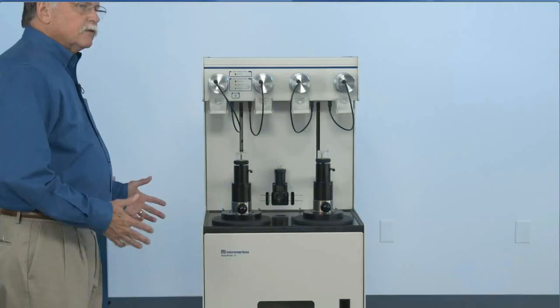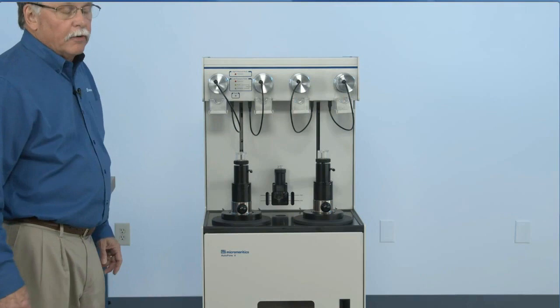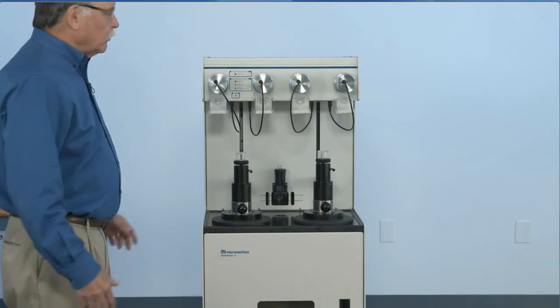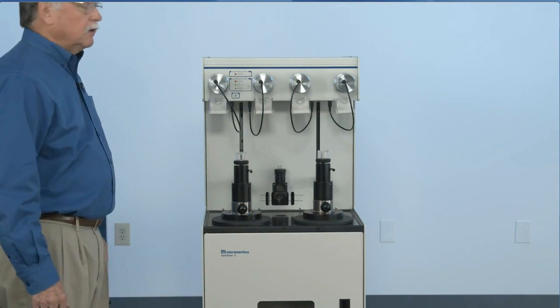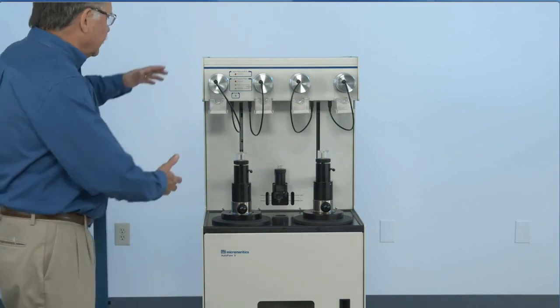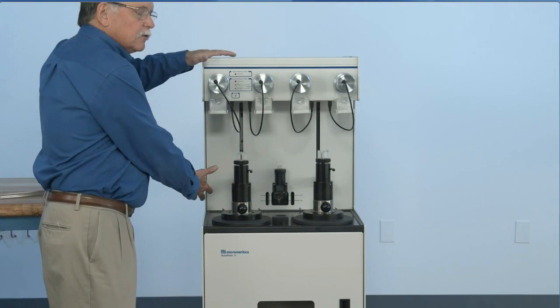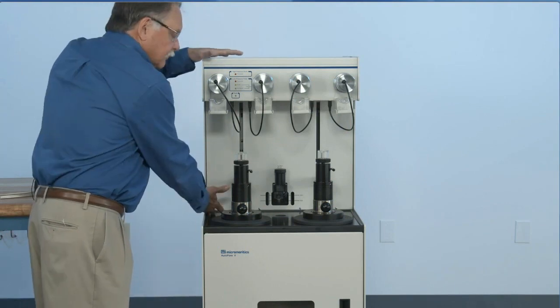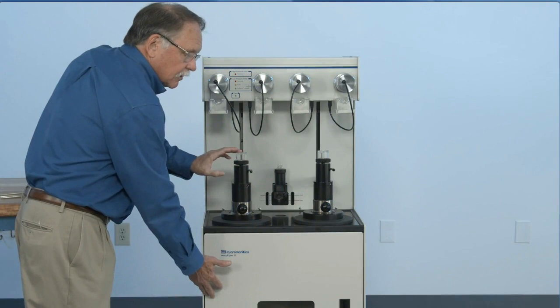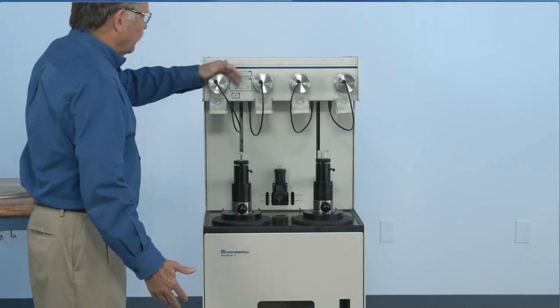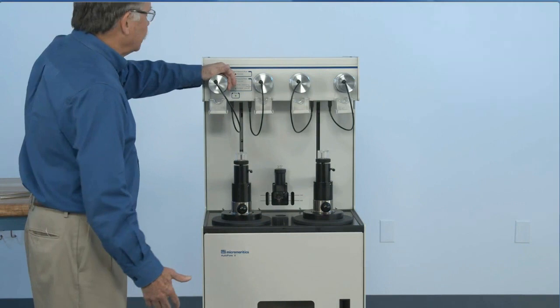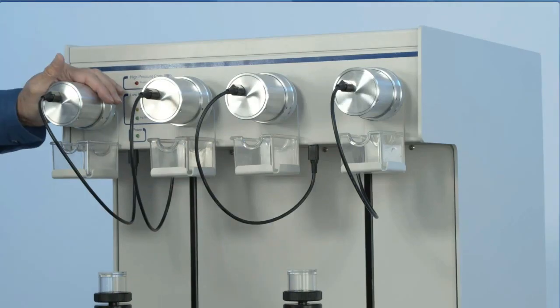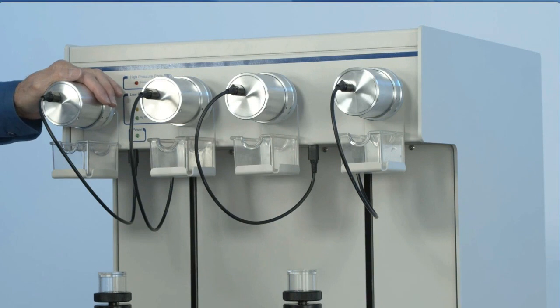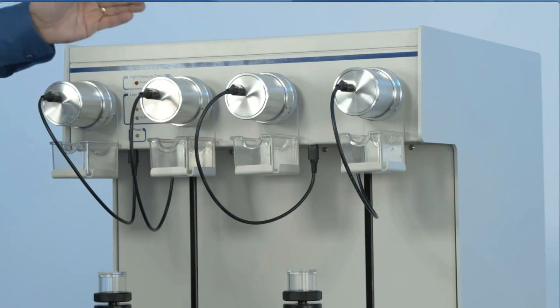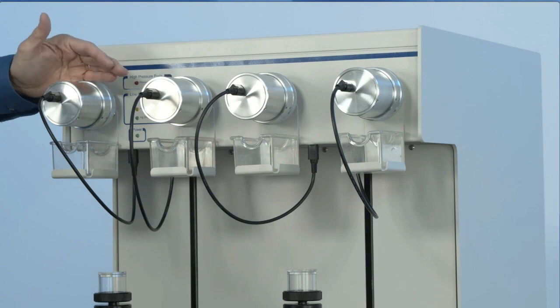So I want to take a few minutes to introduce you to the hardware of the AutoPore. We're going to look at software in a bit, but I did want to take you through the features of the AutoPore hardware. And basically the AutoPore, it's like having two instruments in one cabinet. We have a low pressure system on top and the high pressure system on the bottom. The low pressure system takes care of evacuating air from the sample holder. It does introduce mercury into the sample holder, which we call penetrometers, and then it performs the analysis from subambient pressures up to about 2 to 3 atmospheres, which is user selectable.